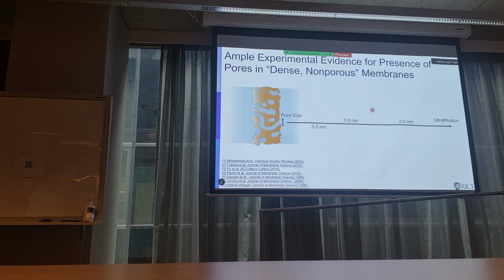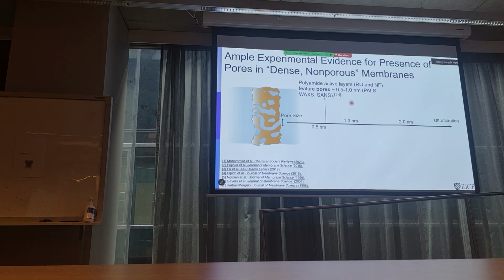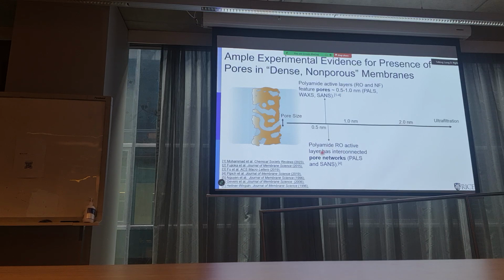Okay, this is just a list, and again, I sent you the PDF of this lecture. You can just click on this, and then you will open the article. There were some studies using PALS, WAXS, and SANS, these very advanced techniques, and they show pores between 0.5 and 1 nanometer for reverse osmosis and nanofiltration membranes. Even the same group, like reference 4, found some interconnected pore network. Sometimes they are just void pores, but many times they are interconnected.